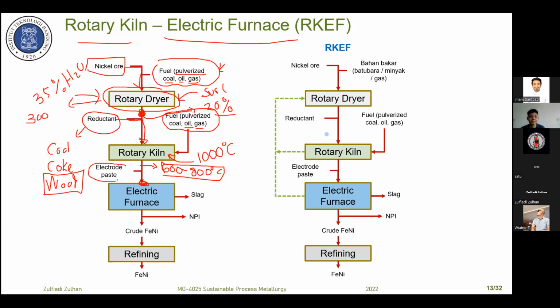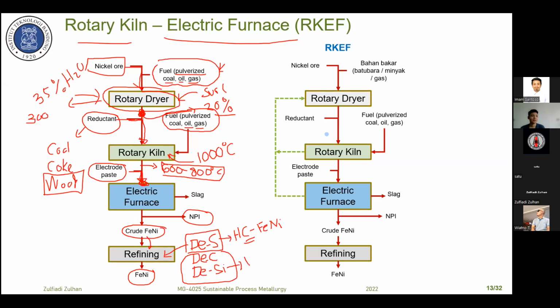We form the electrode from electrode paste and graphite, and the product we get is NPI, or crude ferronickel, which is then refined further into ferronickel. Usually here we use desulfurization. In some plants they also use decarburization, and desiliconization can also be conducted, to remove the silicon. If we do only desulfurization, the product is called high carbon ferronickel. If we remove the carbon by oxygen blowing in a converter, we can also produce low carbon ferronickel.